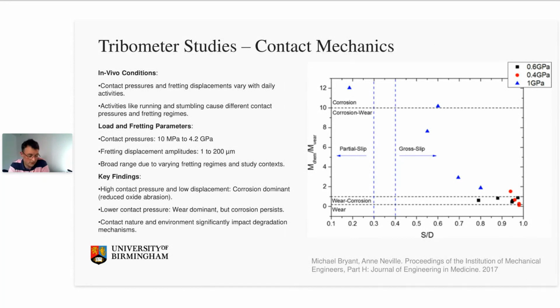But as the contact pressure and the slip decrease, we can see that wear, or the physical wear, becomes more dominating. But ultimately, what we have found is that we can never escape into a purely wear domain. We always have these elements of wear corrosion or corrosion wear taking place, and it's usually the case within the biomedical domain that we're within this corrosion wear domain or within the corrosion domain, which presents some interesting challenges in terms of how the material is released from that interface, whether it's debris or whether it's ionic.